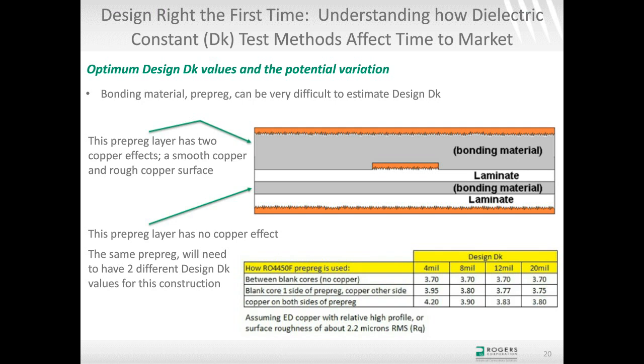So the top ground plane and the signal in the middle, that bonding material is actually seeing roughened copper on the top side and smoother copper probably where it interfaces with the signal plane. So that's a little bit trickier. And I've given a table of information here if you're using the RO4450F prepreg. And this is just a reference. It's a pretty good reference just from doing a lot of studies on this topic. But again, if you're not comfortable with these type of issues on a stripline structure or any kind of mixed material structure, then please contact us and we'll do what we can to help you.